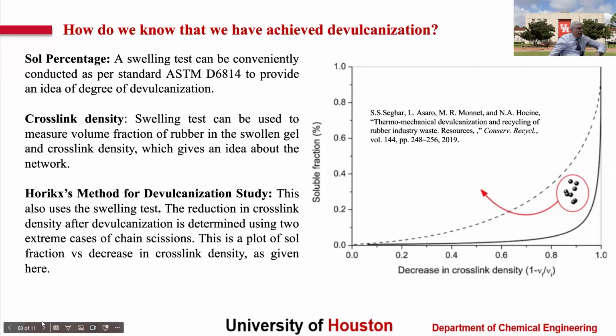How do you know that you have achieved devulcanization? When you do devulcanization, you get lots of polymer back into the rubber compound. So you can measure the sol percentage. That means it goes into the solution. Those particular polymers that are released will go into solution. And you can measure that by ASTM D6814. And then also you can measure the crosslink density, which gives you an idea about the network. That means before, what was the network and crosslink density? After you devulcanize, what is the network structure? And that gives you an idea.